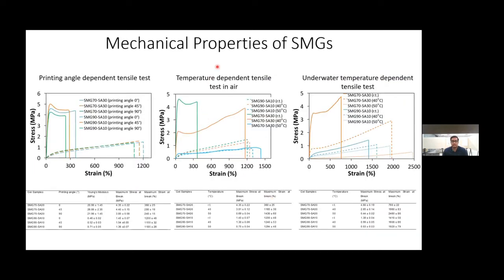Here are the mechanical properties of SMGs, and I have examined the printing angle dependent tensile test, and this portion represents SMG 70 SA30, where the crystalline concentration is higher, and it shows somewhat rigidity. And this portion is for SMG 90 SA10, where the amorphous concentration is higher, and it shows somewhat flexibility. And we didn't find any change in mechanical strain for changing the printing angle from 0 degree to 90 degree.